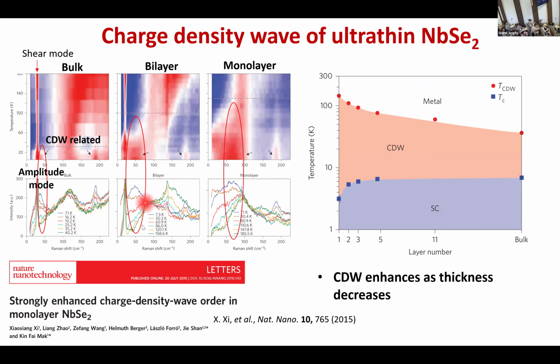And then people just around the same time. Actually, this paper appeared before, so they first tried some optical measurements, which was experimentally, I think, easier. And then they measured the charge density wave. In the Raman spectroscopy, there are some features here and here, and these features correspond to the charge density wave. I think one way experimentally is that these features just disappear when you increase temperature above 33 Kelvin, above this charge density wave temperature. And this one is well established that people observed that quite some time ago in bulk niobium diselenide, which is corresponding to the so-called amplitude mode of this charge density wave. So the amplitude gets excited at this particular frequency.